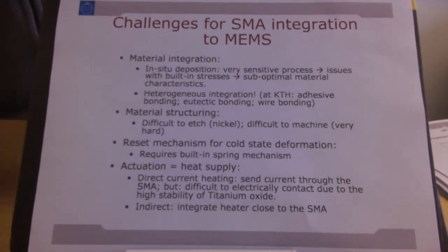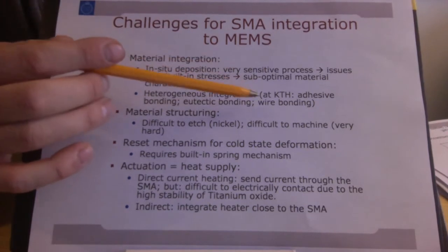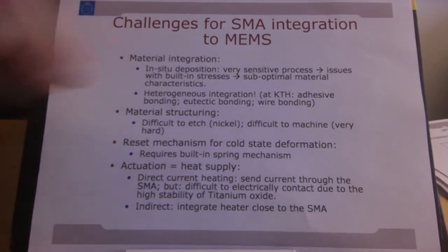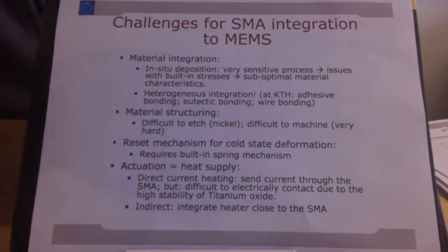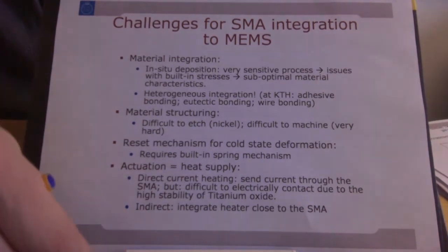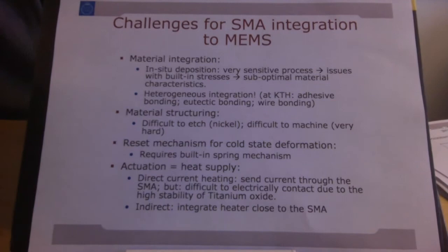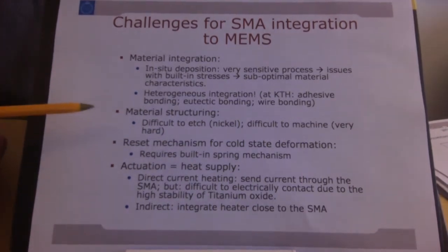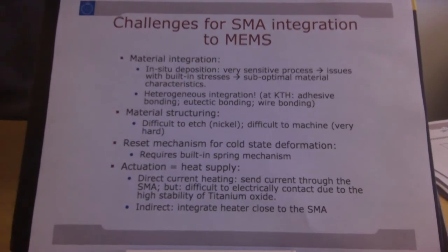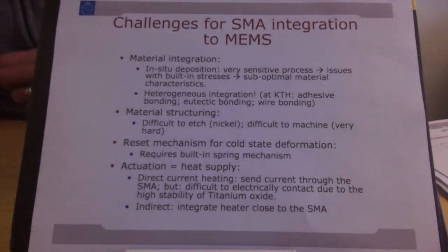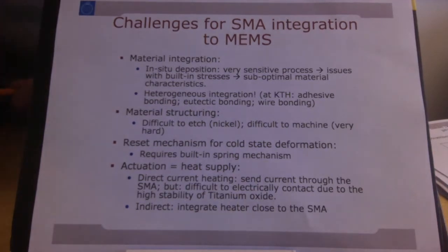At KTH during the past 10 years, my group has focused a lot on specifically doing that. And this integration we do either with adhesive bonding, or using eutectic bonding, or using SMA wires and a wire bonder. So instead of using a wire bonder for contacting chips, as you're going to see in the lab, instead of using little gold wires for contacting MEMS structures electrically, we're going to put an SMA wire in the wire bonder and use it to integrate wires onto the MEMS. I'm not going to go into detail on how this is done. So there are ways of integrating the material, but they're typically not standard, rather expensive, and/or very specialized.